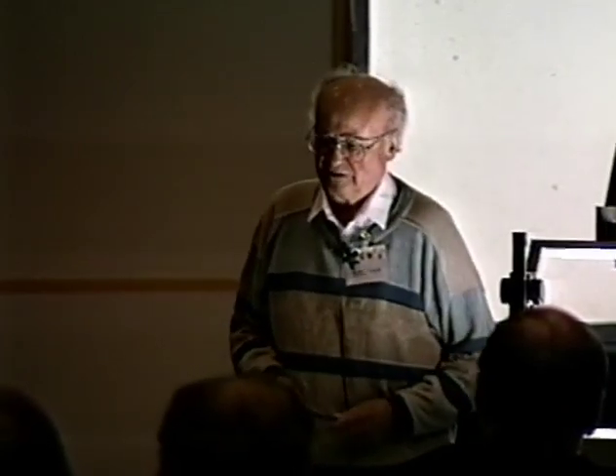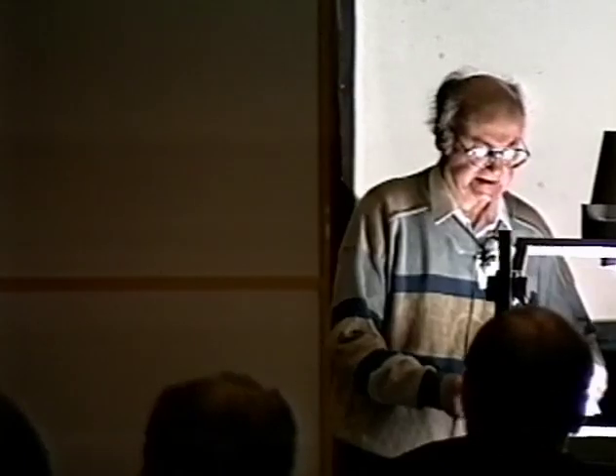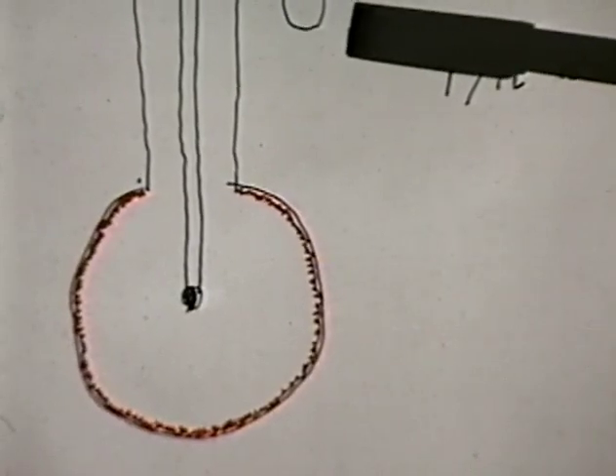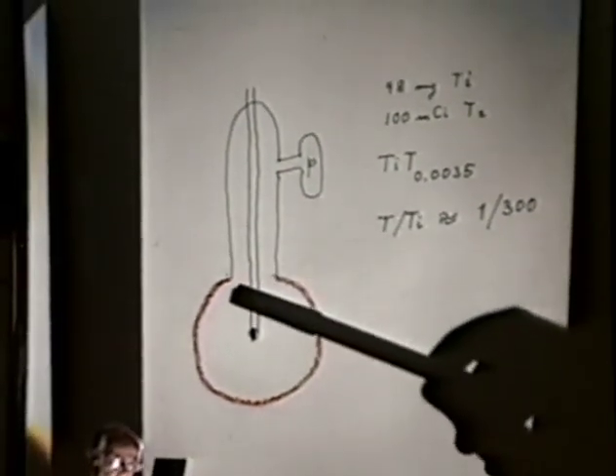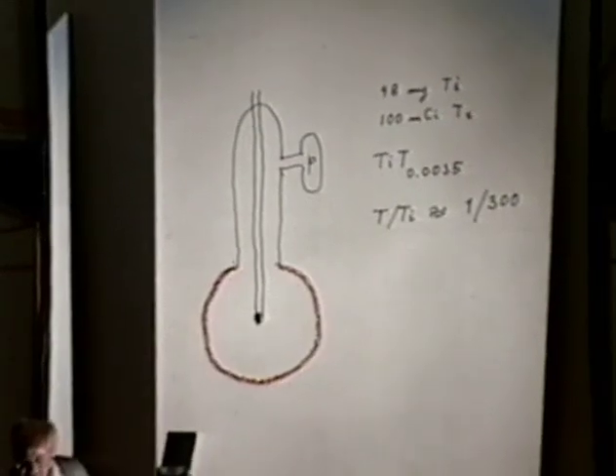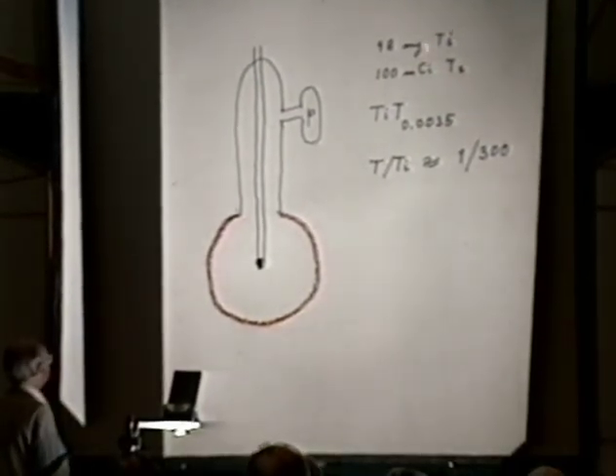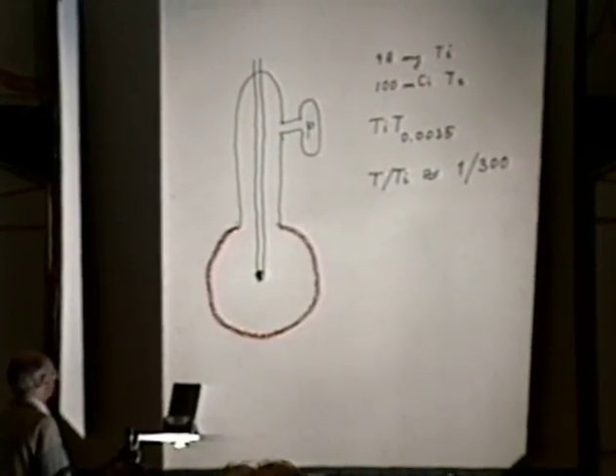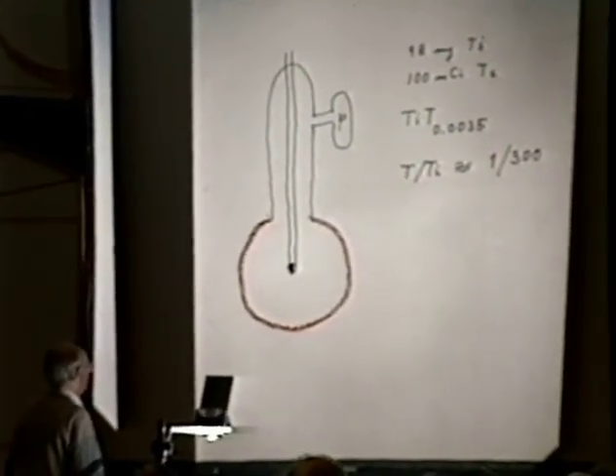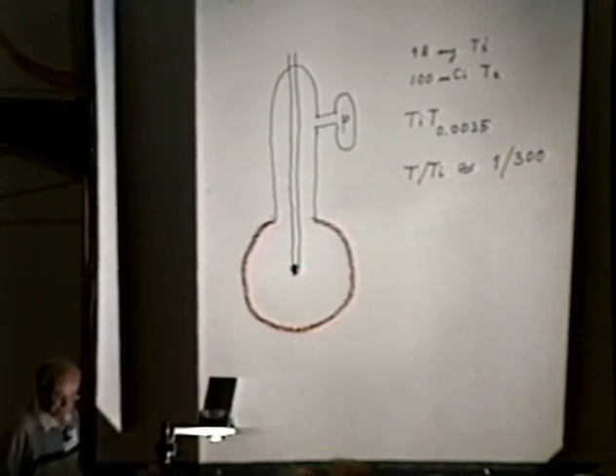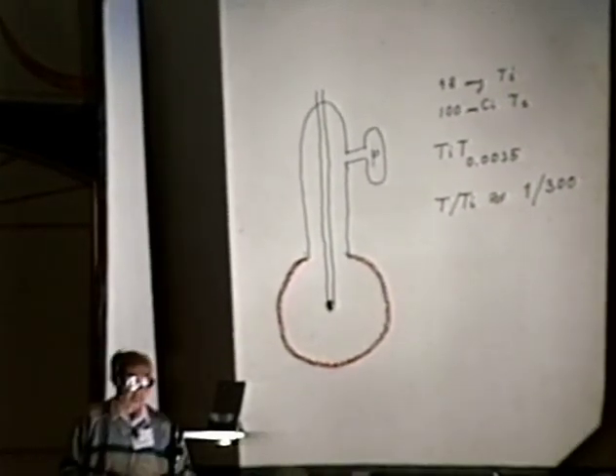We thought about a better method to measure the temperature stability. This can be done with two ways. One method is to increase the temperature of the preparation in a vacuum tube and to measure the pressure rise of the tritium pressure. We have made here a titanium preparation, 48 milligrams titanium, 100 millicurie tritium. This is a preparation. The atomic ratio is 1 tritium atom to 300 titanium atoms. And during increase of temperature, we measured the pressure of the tritium, which was released.